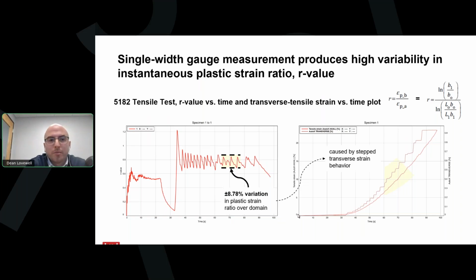So this is that same test from before, the 5182 alloy, and it's exhibiting the PLC effect through the strain hardening region. Here, instead of looking at a stress strain plot, I've chosen a Blue Hill chart that shows R value plotted over time, as well as the contributing strains over time. And then I've highlighted the domain that's used for plastic strain ratio determination for this alloy, which is 8 to 12% axial elongation. In this area, there's almost 9% variation over the range.